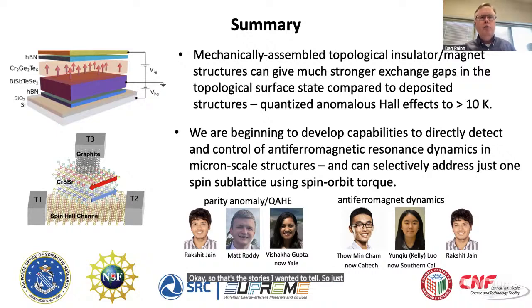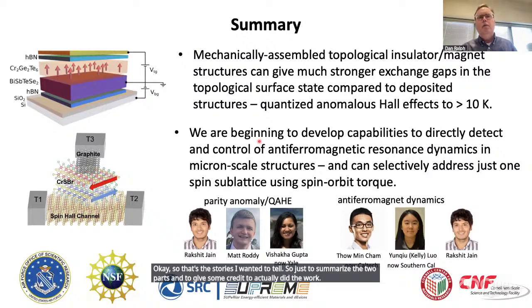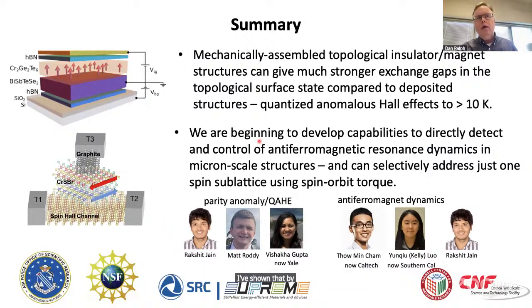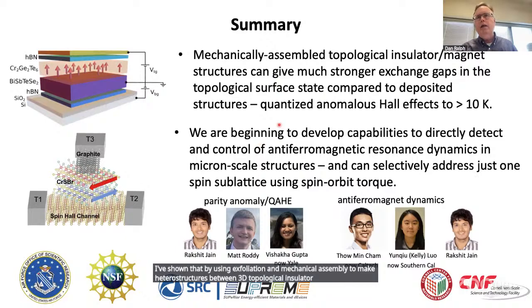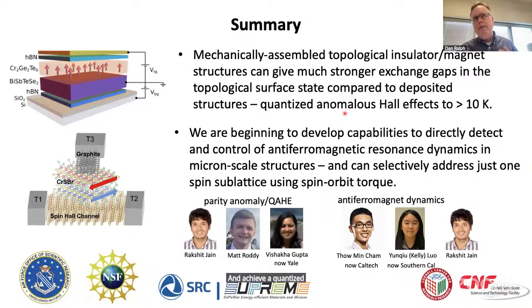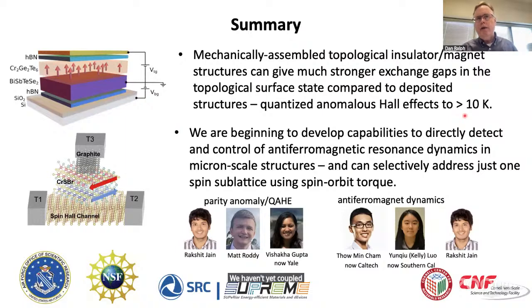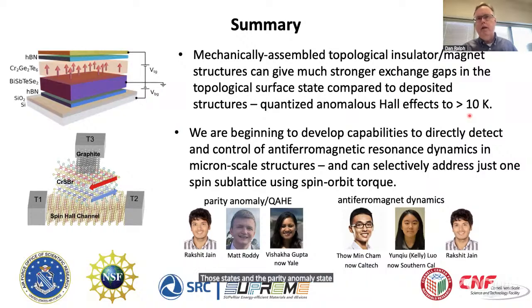So just to summarize the two parts and to give some credit to who actually did the work, I've shown that by using exfoliation and mechanical assembly to make heterostructures between a 3D topological insulator and an insulating magnet, we can achieve much stronger exchange gaps than what's been done previously through MBE grown structures, and achieve a half quantized anomalous Hall effect in the parity anomaly regime at temperatures up to greater than 10 Kelvin. We haven't yet coupled magnets to both sides of the topological insulator to have a fully quantized state with dissipationless edge channels, but at least for the magnetically doped topological insulators, those states and the parity anomaly state have the same temperature scale. And we're very optimistic that with some improved device fabrication, we'll be able to see those kinds of physics too.